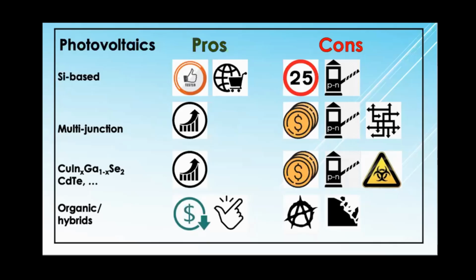manner. So there are alternatives and other semiconductors, and the semiconductors that use selenium, cadmium, tellurium are really performant, but have problems with environmental issues, rare materials, expensive materials. They also work in the same way as semiconductors with a p-n junction. So the most promising materials now for photovoltaics are organics and hybrids. And the cost is very low. They appear to be the solution, but in fact, they are facing lots of problems with stability and homogeneity. And most of them, as organics, will not stand high temperatures or even UV light.